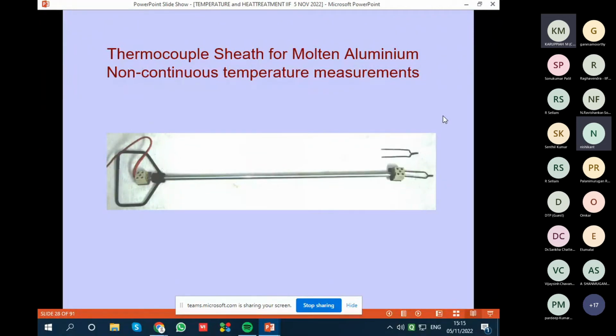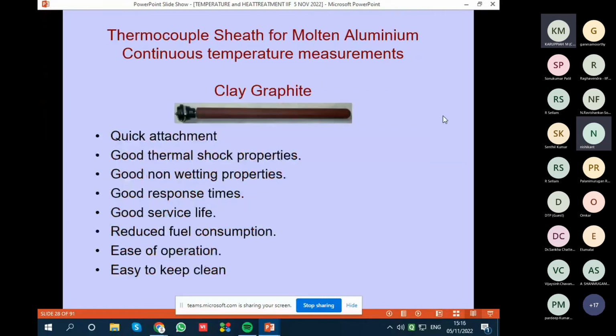It is very economic. And just like multi-dip, this thermocouple can be used again and again. Only you have to remove the thermocouple from the front side and replace it. About 25 times you can use it in your plant. So in any induction furnace where you are melting aluminum, you can measure this quickly. That is why it is very popular for quick measurements. But if you have a melting furnace as well as a holding furnace, then in the holding furnace, you have to use a continuous type measurement.